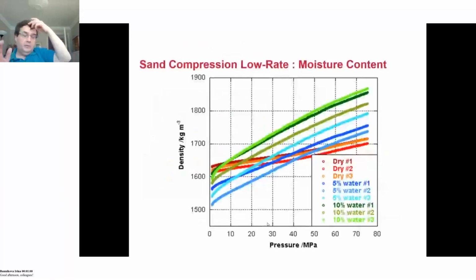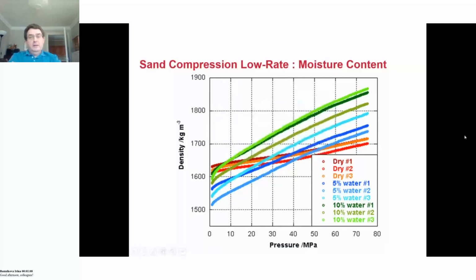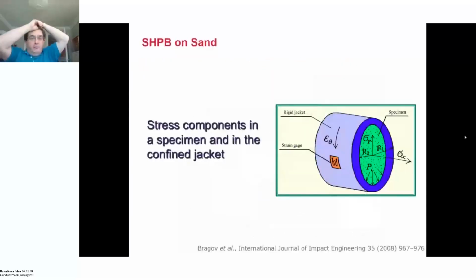Now, if you revisited the data for, say, low rates, adding the water, you can get this kind of response. And again, just showing this graph to say that once you lubricate those crystals by having a little bit of water present, you can get a whole lot more compaction going on, as is shown here, where the dry material is going in the red lines and it's fairly flat, whereas the moistened material shows significant density increase. Okay, so far reasonably okay, but can we go to higher rates?